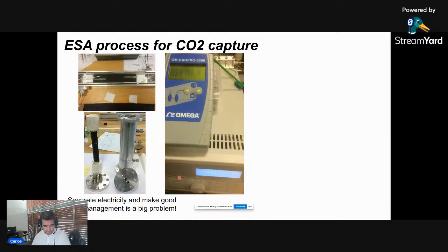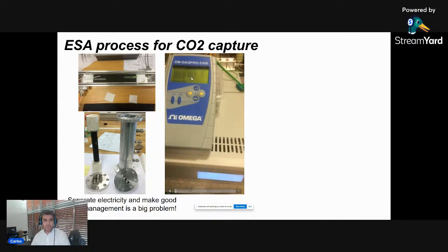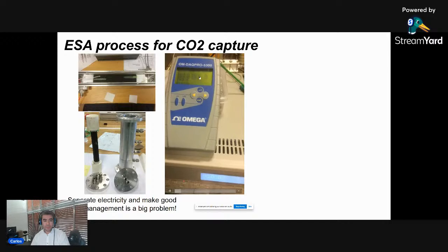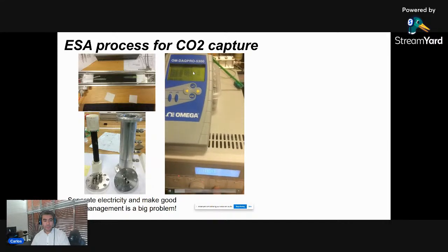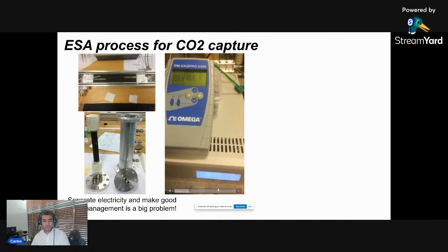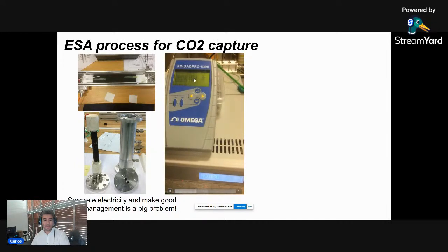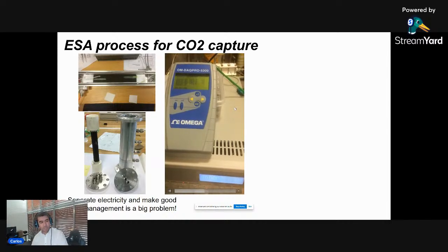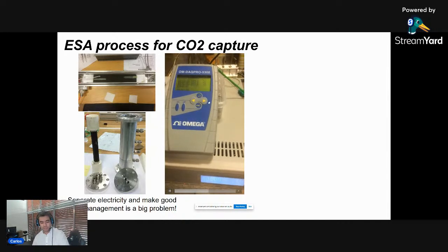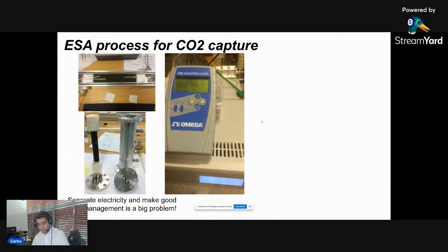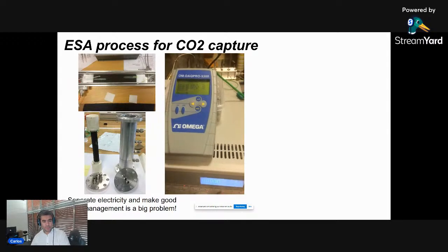I don't know if this video will work, but you can see, I don't know if the screen is very big, this is a very raw video that we made when we started putting 80 volts. You can see my finger here starting, and the temperature increases 30, 40, 43, 46, 50. We really achieved something like 120, 125 degrees in the order of, I don't know, 30 seconds. So it's really unbelievable what you can do when you can get a good conductivity through these adsorbents.